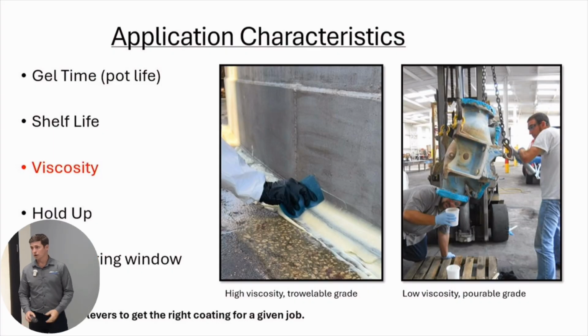And then overcoating window. So overcoating window is particularly important, and it's something that we understand as a coating manufacturer and applicator. Overcoating window is related to the polymerization rate of the coating. At higher temperatures, that polymerization rate increases, which thereby the overcoating window decreases. The overcoating window is essentially when you put one coat on, how long do you have to put the next coat on, and then cross-polymerize. So you have a chemical bond between.